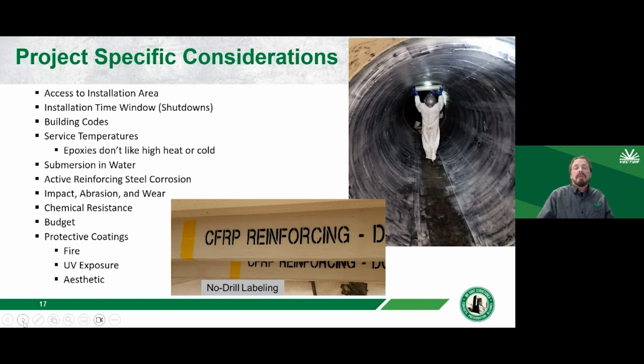Active reinforcing steel corrosion. So typically we'll see this in bridge construction or a maritime environment where we've got de-icing salts and we know that we have active corrosion going on of our reinforcing. Chlorides are at the level of the reinforcing, so we want to do something to mitigate that. That might be a galvanic anode prior to installing FRP. It is chemically resistant in a lot of different ways, but if you're using it in an industrial facility with a different chemical exposure, we want to make sure that that's accounted for as well.